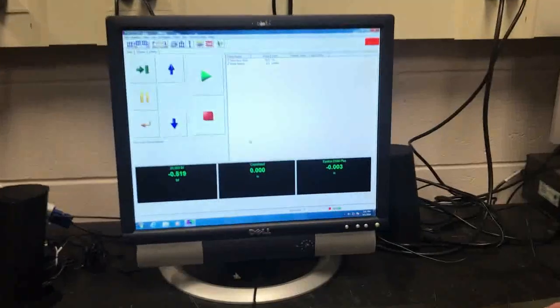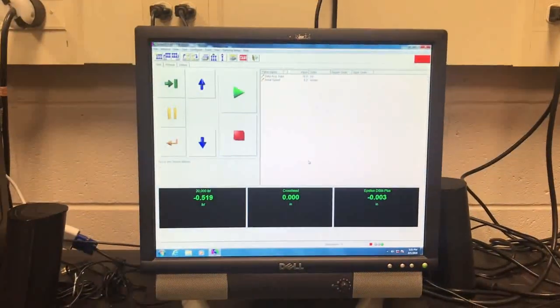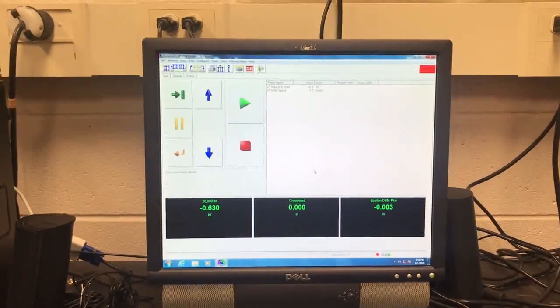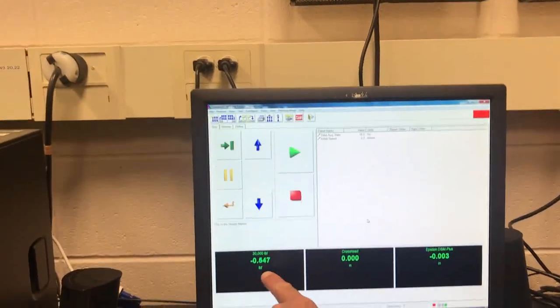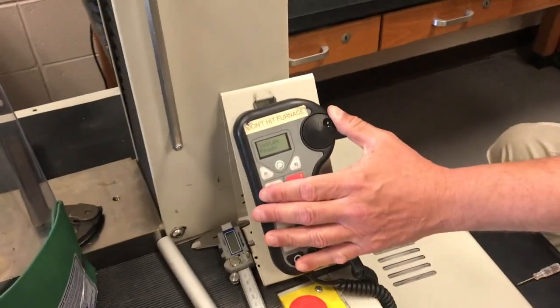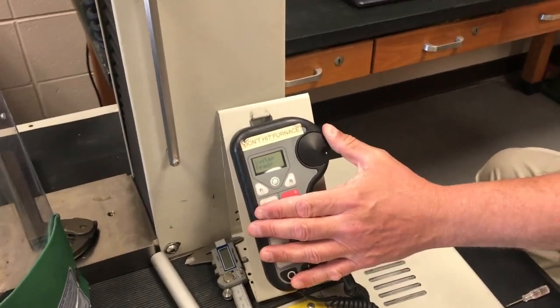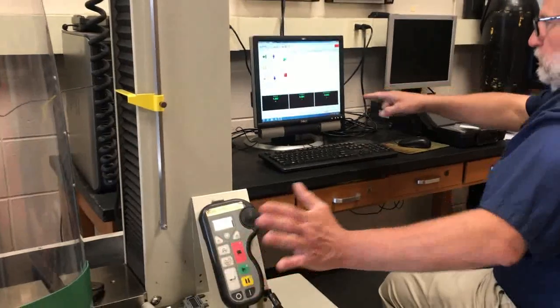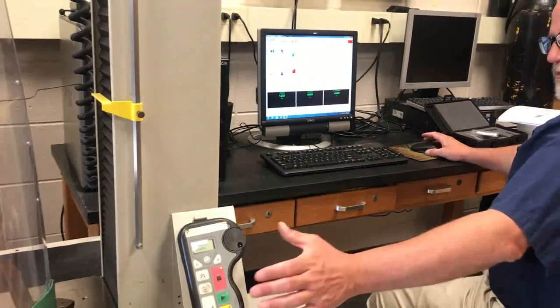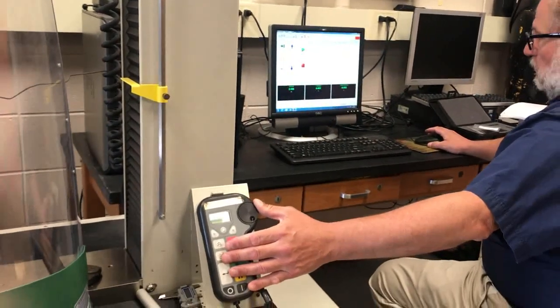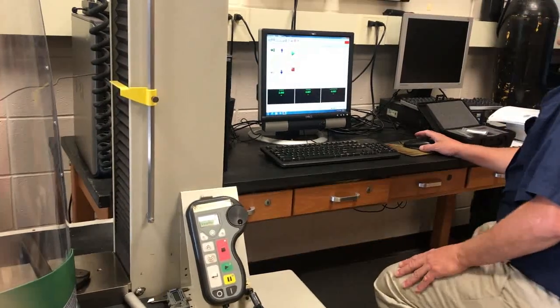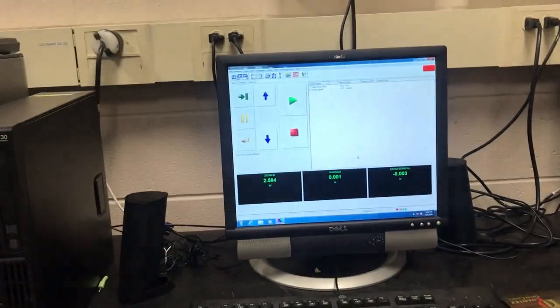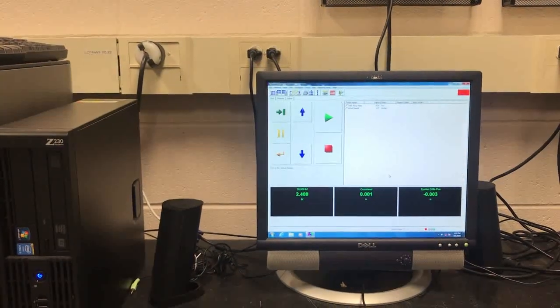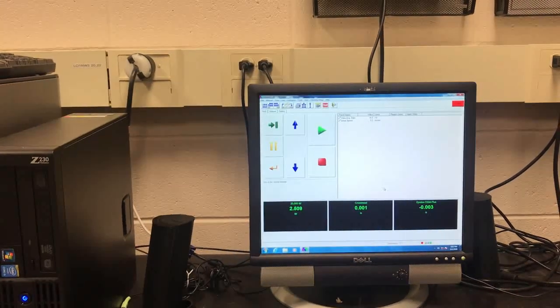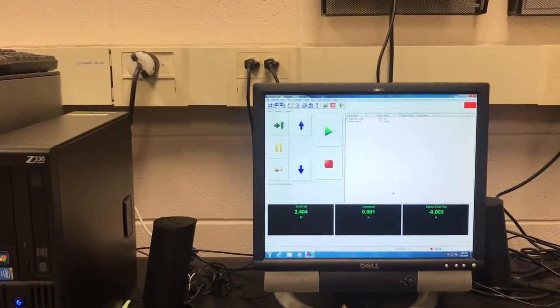And there's one more thing, well, there's several more things we want to do, but one of them is to eliminate any slack or play in the test rig. So watching the force indicator, which is essentially 0, come back over here to the control panel and gently move the crosshead until you see the force go into positive territory, positive numbers. Right now it's about 1 pound. So I'm gently, very slowly moving the crosshead, and the fact that it's indicating a positive force tells me that there's no play in the test assembly, because any slight movement of the crosshead up results in the indication of force. I hope that makes sense.